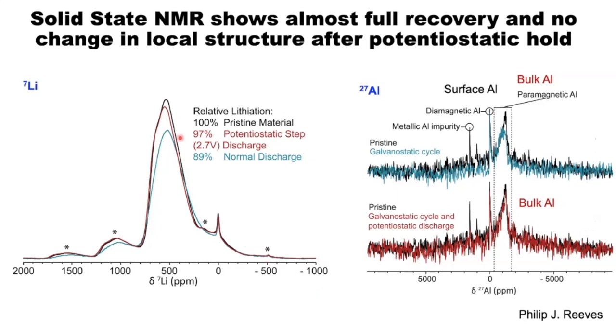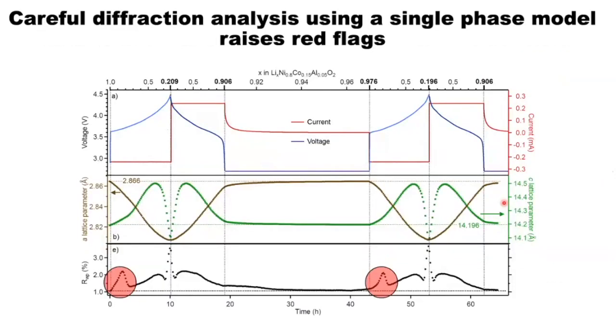And so in work that Phil did, he showed that if you hold the material again at a constant voltage of 2.7 volts, you get almost all the lithium back in again. And you can see this via the lithium NMR, and you can also see this by the aluminium or aluminum NMR, depending on where you are in the world. And the aluminum NMR is very sensitive to both the surface impurities, but it's also sensitive to the aluminum or aluminium in the bulk. And you can see that only on holding at 2.7 volts do you get all of the aluminium back in again.